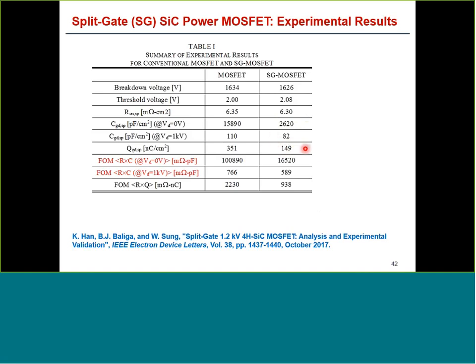So if you apply this and calculate these various figures of merit, you find that you get a 6x improvement in the RC figure of merit if you use the 0 VD value, and a 1.3x improvement if you use the 1 kV value for CGD. If you use the QGD values, then you get an improvement of 2.4x.